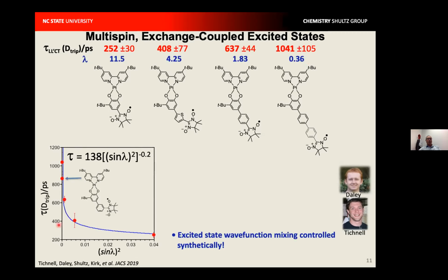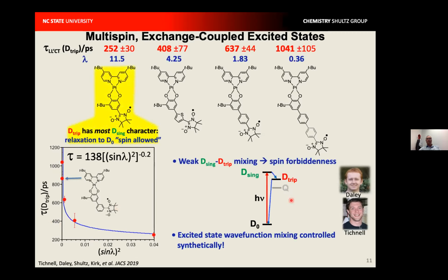And so what we demonstrated was control of the charge separated excited state lifetime with exchange coupling, which in turn varies the mixing of D-sing and D-trip. And so we can really understand this by the fact that when the mixing between D-trip and D-sing is large, then D-trip has a lot of chromophoric singlet character to it, and the non-radiative decay back down to the doublet ground state is very fast.